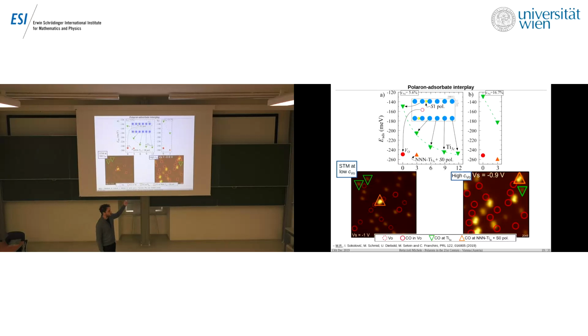But it's half an electron volt with a U of 4, which I think is a fair assumption. And half an electron volt is quite big. If you look at our polaron formation energies in titanium dioxide, where we also use a U of 4, the energies are much smaller than 0.5. So I would say it's pretty safe to say that there is a polaron there.